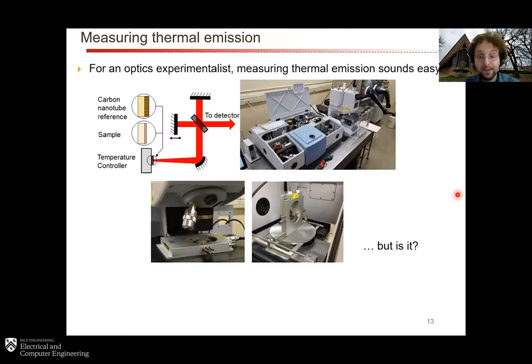experimental situations. So I'm an optics experimentalist, and for an optics experimentalist, the concept of measuring thermal emission sounds like it should be really easy. Conceptually, it's very straightforward. You take a sample and you put it, for example, on a temperature controller so that you can change the temperature to whatever you want, you know, 100 degrees, 200 degrees, 50 degrees, room temperature, and so forth. You send the output into a spectrometer. In this case, in the mid-infrared, we typically use Fourier transform infrared spectrometers, or FTIRs, because of their multiplex advantage compared to, for example, grating-based spectrometers.